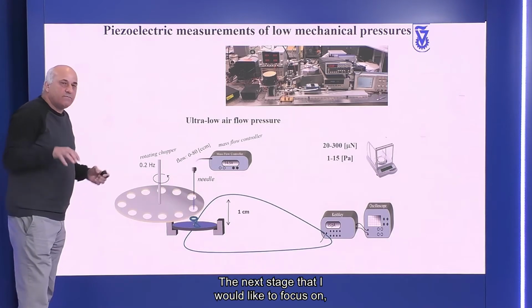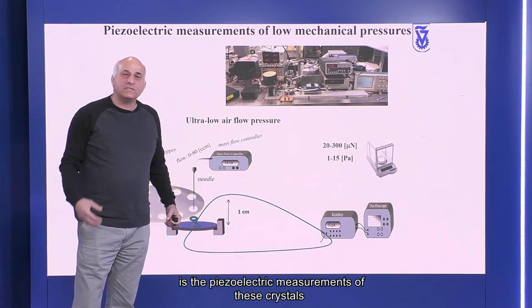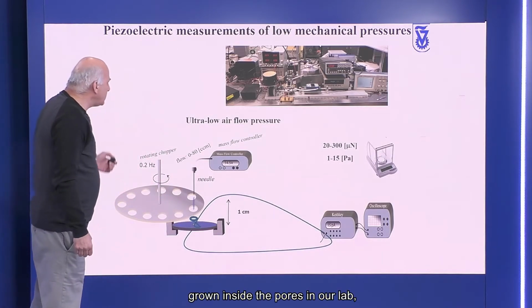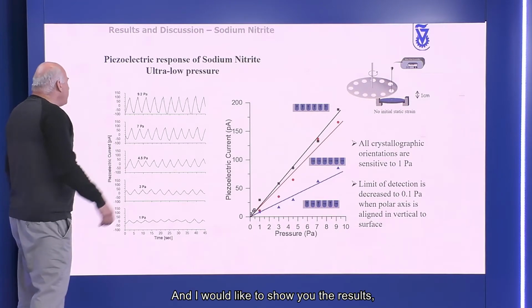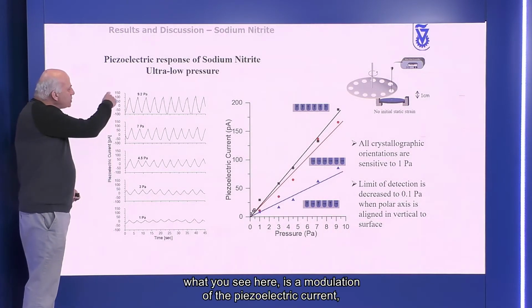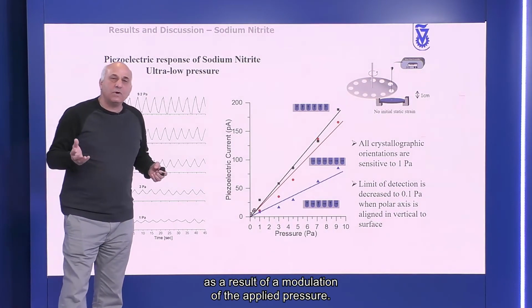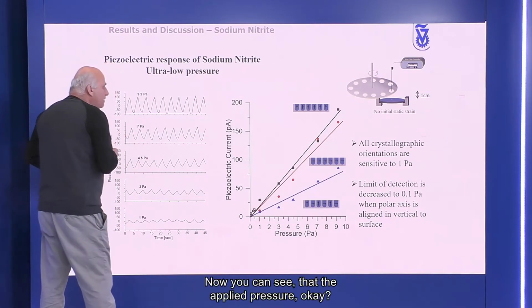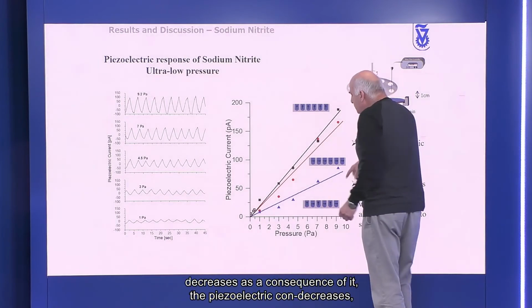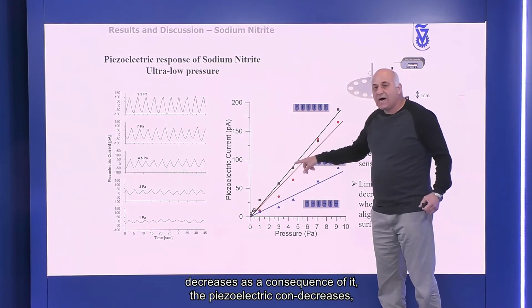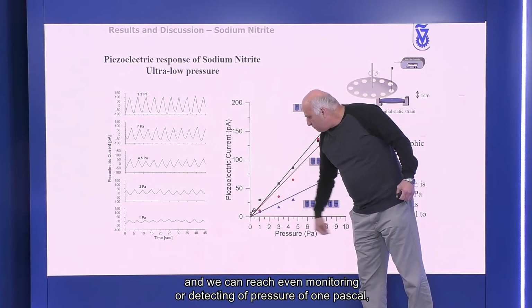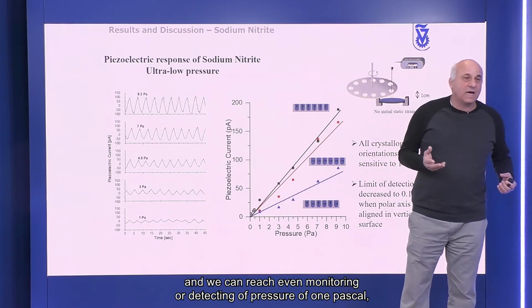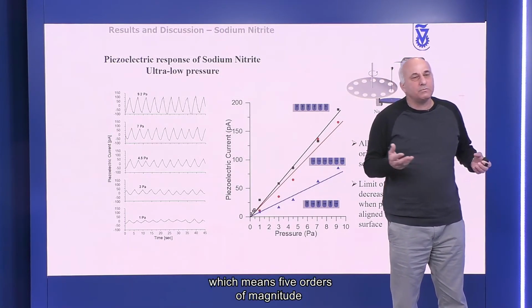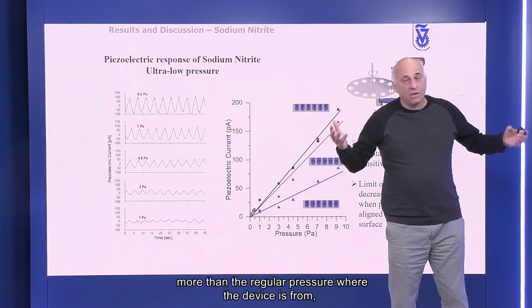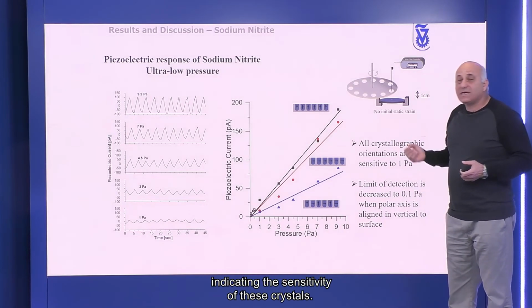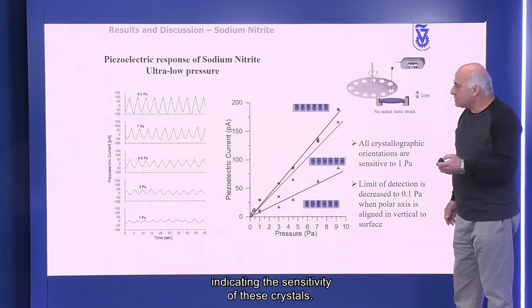The next stage that I would like to focus on is the piezoelectric measurements of these crystals grown inside the pores in our lab. This is the setup, and I would like to show you the results. What you see here is a modulation of the piezoelectric current as a result of a modulation of the applied pressure. Now you can see that the applied pressure decreases. As a consequence, the piezoelectric current decreases, and we can reach even monitoring or detecting of pressure changes of 1 Pascal in an environmental pressure of 1 atmosphere, which means 5 orders of magnitude lower than the regular pressure, indicating the sensitivity of these crystals.